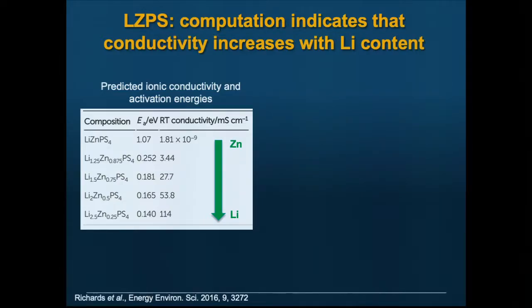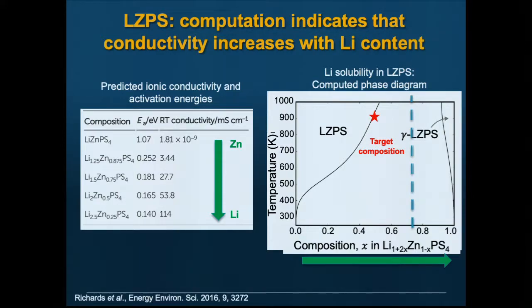So remember, that's a factor of 10 above the best known solid-state lithium-ion conductor there. But as always, nature is against you, right? And so it turns out if you calculate the phase diagram, this is LZPS, this is a solubility limit, this is the lithium content. Our target composition, the optimal composition, is right in the 2-phase region, right? So if anything, we would have to make a really metastable compound that sits in the 2-phase region. So we have never been able to actually get to that composition.